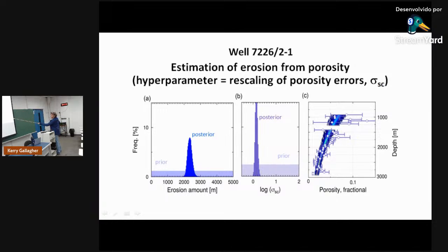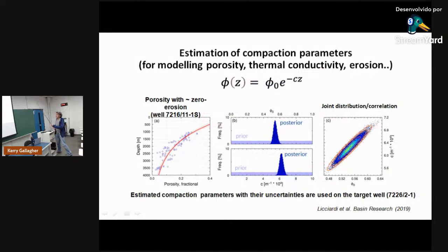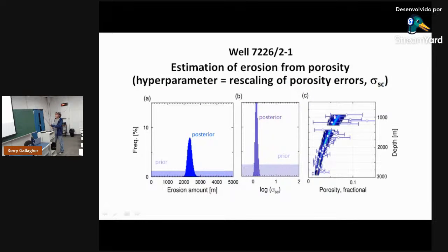So these are the data that we fit, and if you look here just on the scale at say 1,500 meters, we're at about 0.05, 5% porosity at 1,500 meters. If we go back to our calibration well, at 1,500 meters, we're at 20% porosity. That's the idea. We've got this reference curve of normal compaction. We go somewhere else, the porosity is much lower for a given depth. We can try and estimate how much erosion there has been, how much extra burial. And because it's Bayesian, you get a probability distribution on that.